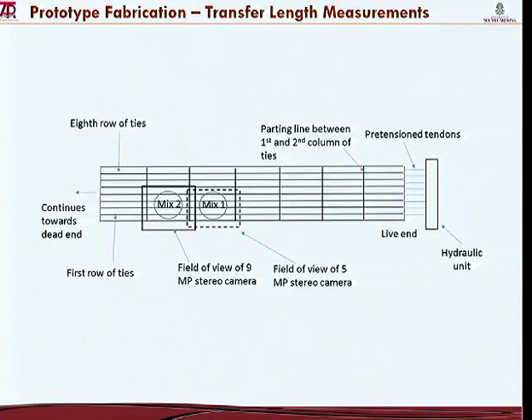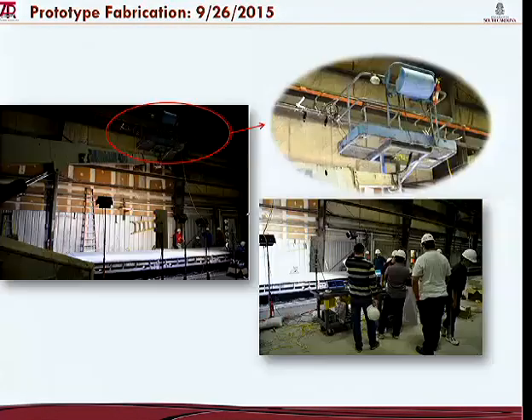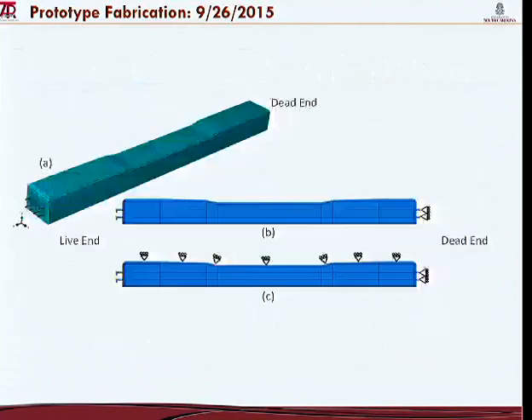The strands run continuously through the bed. So when you cut these strands, the rest of the form, the entire cavity, moves, and it moved by approximately 7 inches. We're looking at the beginning where the hydraulic unit is. So we can find the stiffness of the form and include these effects.